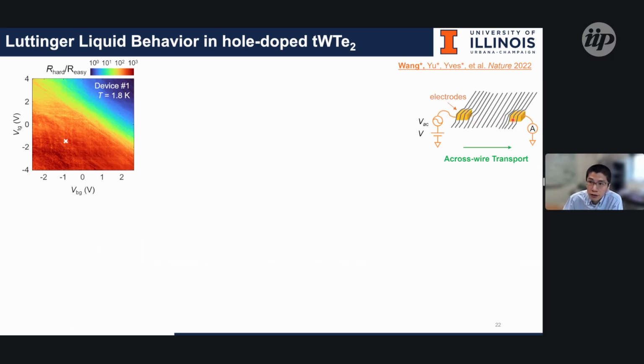For measuring across the wire, there are some contact issues which we try to avoid in the system. With this, we can literally measure the transport property across the structure, rather than measuring the contact effect, as is well known in 1D structures.